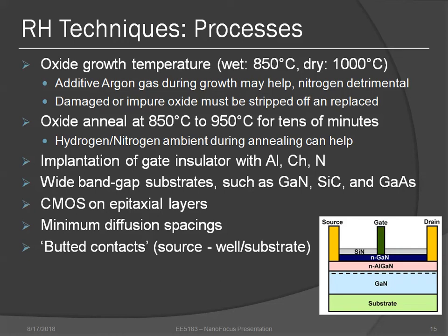850 degrees C to 950 degrees C for tens of minutes. In general, temperature should be kept as low as possible because the highest processing temperature primarily determines the hole trapping response.